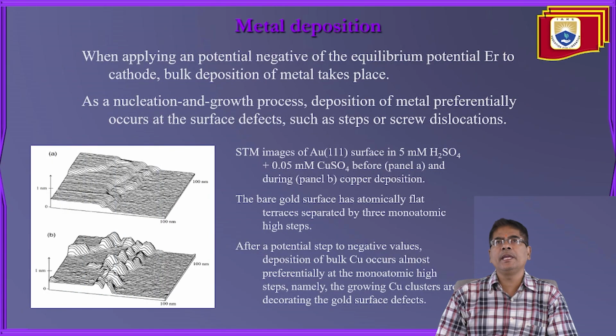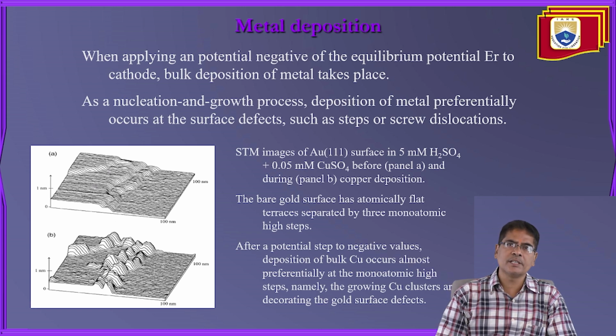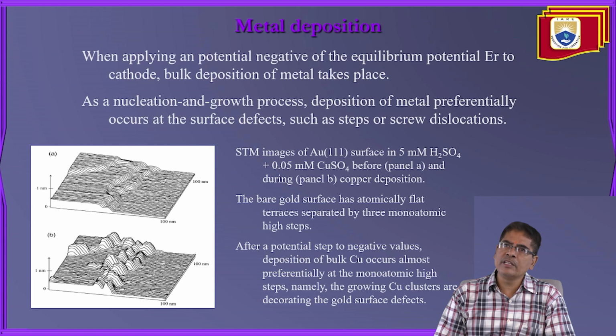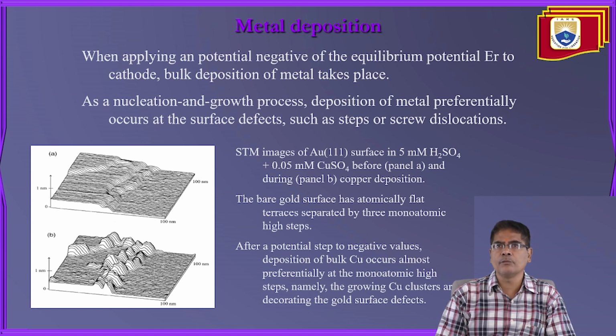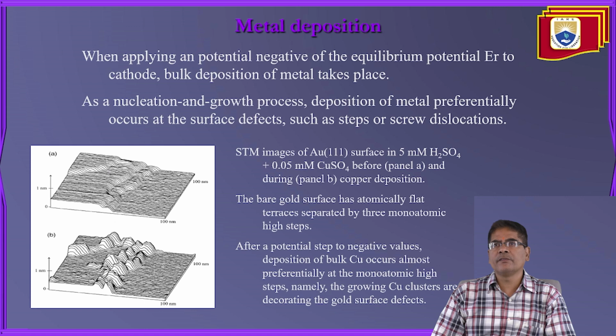So metal deposition: when applying a potential negative of the equilibrium potential to the cathode, bulk deposition of metal takes place, with nucleation and growth processes. Deposition of metal preferentially occurs at surface defects such as steps or screw dislocations. So these are the STM images of gold at the 111 plane, in 5 mM H2SO4 plus copper. The bare gold surface has atomically flat terraces separated by monatomic high steps. After a potential step to a negative value, deposition of bulk copper occurs preferentially at the monoatomic high steps, namely the growing copper structures are decorating the gold surface.